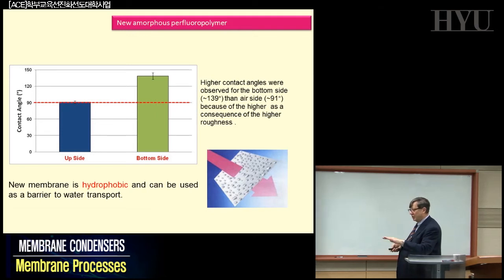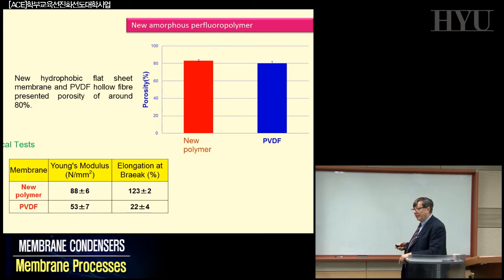That means these are flat sheets at the moment. Bottom side means on the glass plate on which you are condensing, and the other one on the upper side. This material is strongly hydrophobic. You can see here that you can have on the bottom side about 130 contact angle, and we learned what contact angle means, 140 in this case, and 90 on the other side. If you now try to analyze this kind of system and understand which one of the two phases is the most appropriate in terms of temperature profile, etc., this is a material that you can handle and try to realize for this specific kind of application.